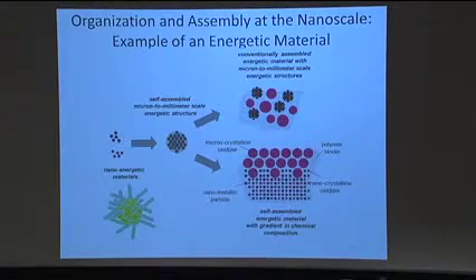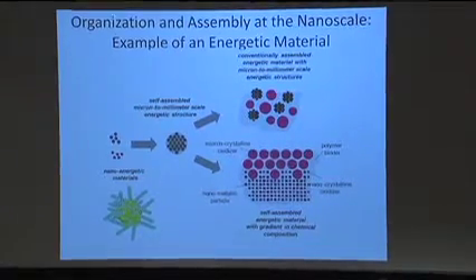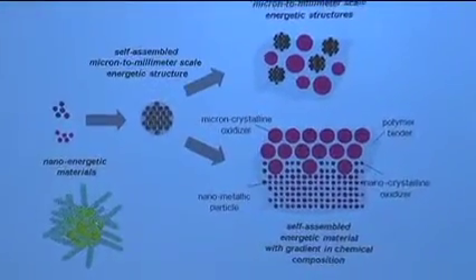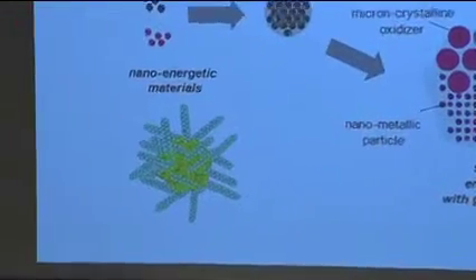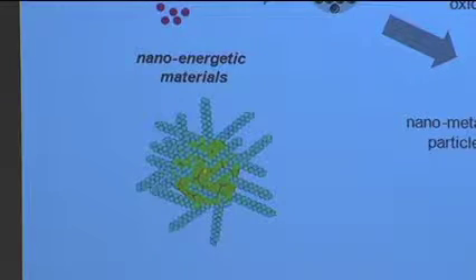So I come back to, say, the nanoscale, and I start looking at my basic ingredient here. Okay? And what I'll show you in a bit, obviously, is the reason aluminum particles and other metallic particles are not pyrophoric is because they have a naturally passivating oxide layer on their surface. But that oxide layer is essentially dead weight. It's already in its final oxidation state, and it's not going to contribute any more to the energy release. So one question you might ask already, is there a way of actually passivating the surface of these small particles with another reactive material? Okay, and what I show here is the idea of actually capping the surface with, say, hydrocarbon ligands, self-assembled monolayers. Okay, and the concept of doing this is if I look at how I bond this ligand to the surface, that energy is going to be related to the ignition energy of this particle. Because when I break that bond, I'm going to start opening up an unpassivated surface to an oxidizer. Okay, so there I've got some idea of how I might start controlling ignition temperatures.